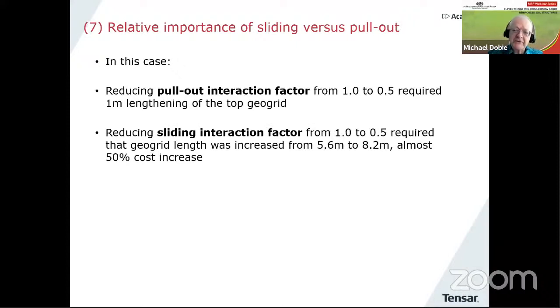I make this point because people are remarkably interested in pull-out resistance, and you get all sorts of research into it, and you get a lot of papers published about it. You get far fewer papers published about sliding interaction, yet that is actually the important one. And luckily, it's the easier one to do because those 30 centimeter shear boxes can be found here and there, but a pull-out apparatus is quite rare.